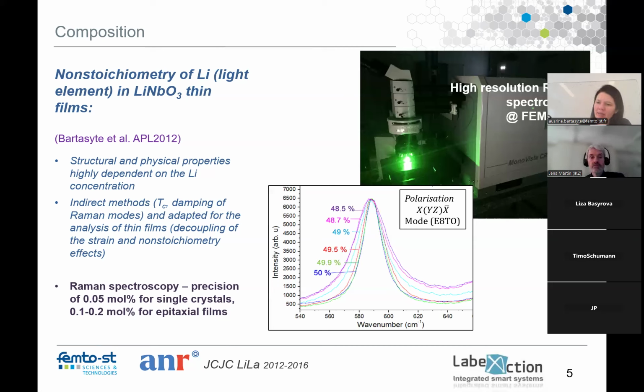But on a relative scale, it's much easier to compare. So it depends a lot, and we cannot always have this precision. But in very high quality, single crystalline quality films, you can probably say more or less, at least, that you have more lithium than a certain value. This is how you can estimate lithium composition.